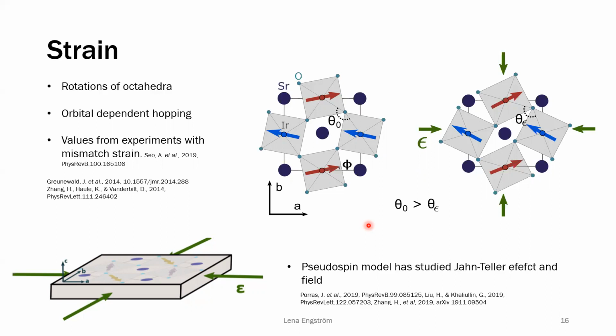Specifically, what we're basing this on is a few experiments with epitaxial strain, which means they grow this compound on a substrate where the lattice parameters are either smaller or larger than those found in this strontium 2 iridium 4. This means you basically change the underlying lattice of the structure. What this means specifically for this material, which basically had to be found from experiment because it's not obvious, at least from our models, is that the effect this has structurally on the system is not that we actually change the bond lengths between the different sites in the square lattice, but we just rotate these octahedra closer or further from each other. So we change this angle.